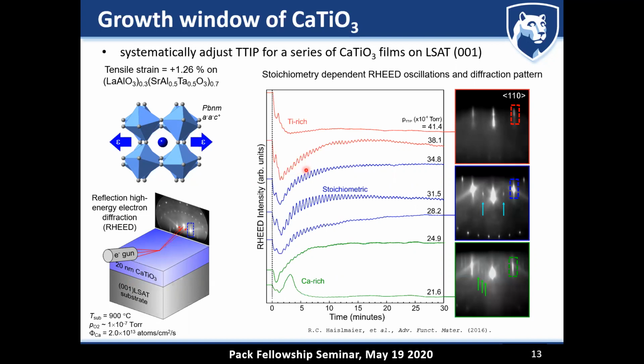And so when we are doing this experiment, where we grow what we call a stoichiometric series, there are a couple of interesting things that we see when we look at the growth using a technique called reflection high energy electron diffraction. I'm showing you here the intensity oscillation as we are growing, typically taken from one of these diffraction spots. And I'm also going to discuss a little bit the type of diffraction images that you see as you grow the film. The things that we find is that, for very specific compositions or very specific flux ratios, we get very good oscillations in the intensity of RHEED. And that indicates that the film really grows in a layer-by-layer fashion.